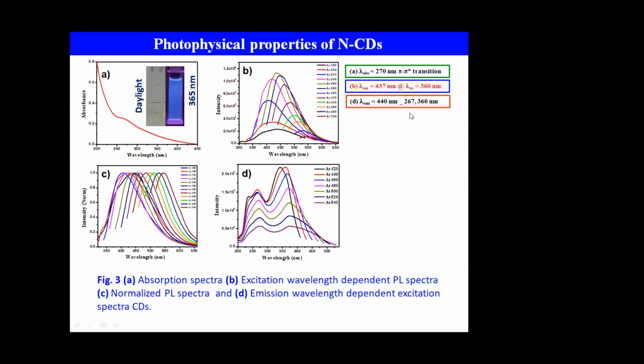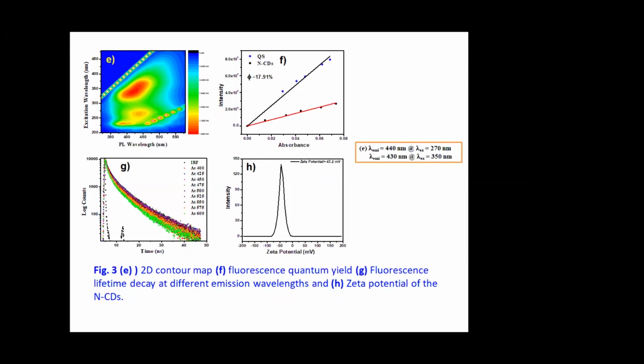Now, when we go on to the photophysical studies, it looks similar to what we have done on the algae material. Only the source material is different, with different size and properties. Again, you can see similar fluorescent behavior, like excitation wavelength dependent fluorescence. I've shown you here the normalized fluorescence intensity, which clearly shows how exactly the wavelength emission maximum changes as you change the excitation wavelength. That is the interesting behavior one can see with carbon dots.